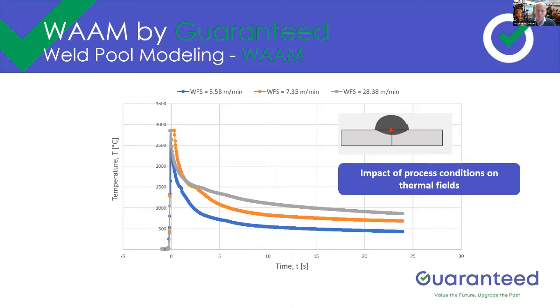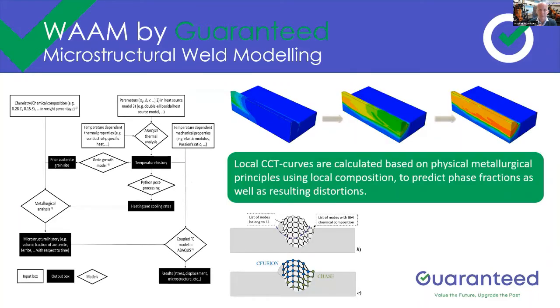but also if you want to control the microstructure, which is actually the next step that I'm showing on this slide, where we developed a full microstructural weld modeling capability as well, where we're predicting on the one hand the local CCT curves based on the local composition, and then we're predicting what type of phase transformations are happening in the material, which then in turn will lead to the warping or the distortion, and where we can then predict between different potential deposition trajectories, which would be the most optimal trajectory in order to avoid distortion altogether.